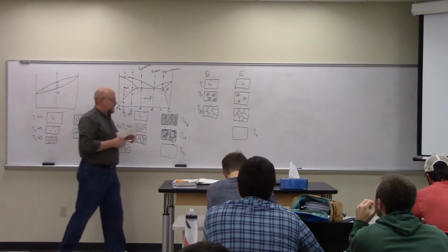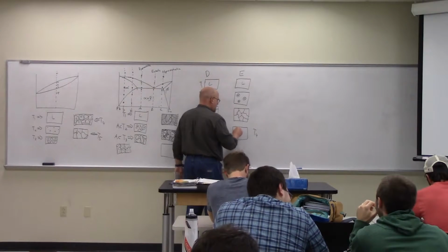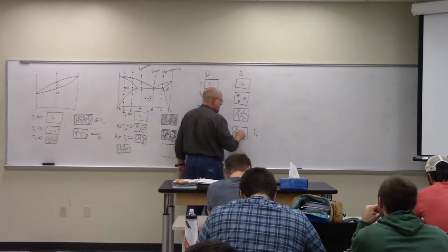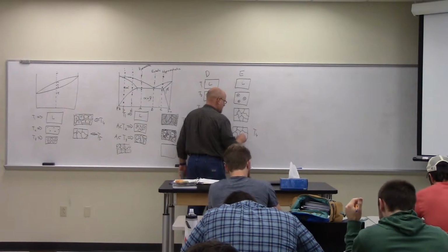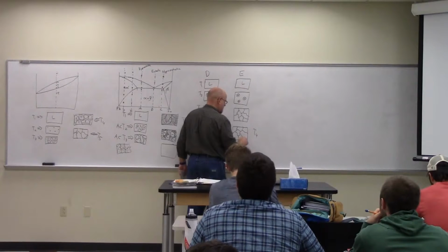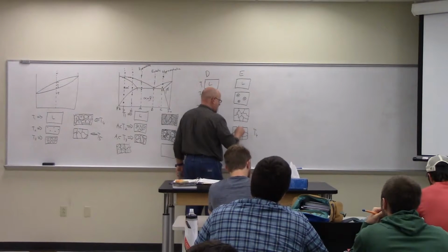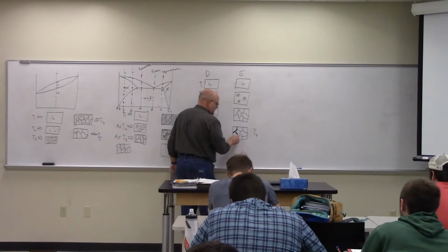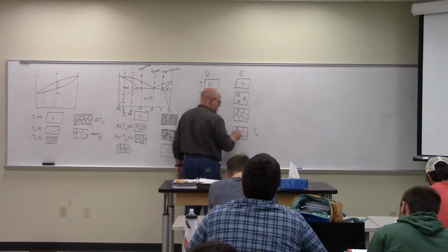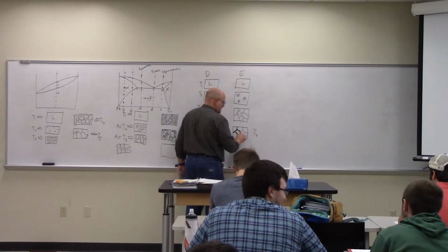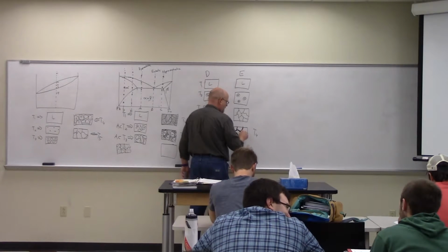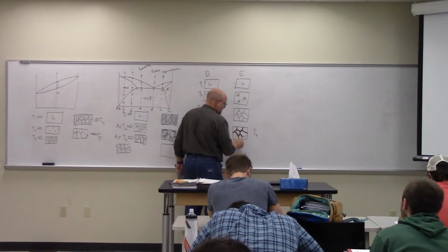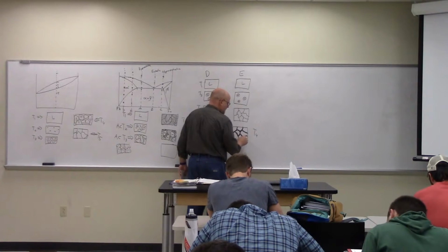Yes, the grain boundaries. So what you get is the same kind of structure, and I'm going to try to draw this the same way I did the other one. But now the grain boundary region becomes decorated with beta material. Remember I talked about the fact that diffusivity was enhanced at the grain boundaries?